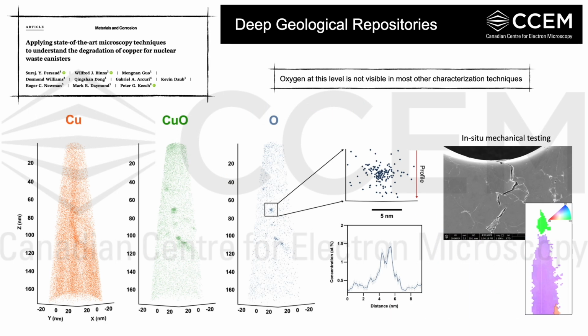And the atom probe data shows clear evidence to support that there is segregation of oxygen, which may be in the form of oxygen or copper oxide at the grain boundary, and this might be happening during the deposition process. And this segregation of oxygen may have no effect on material performance, or it could be important for both high temperature and corrosion performance. So this work was kind of the first steps and is mostly qualitative.